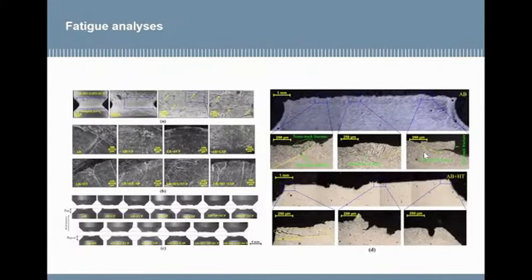Apart from the improvement in the fatigue life of the samples that I'm showing in the next slide, what was interesting is that we expected the fatigue fracture to happen from the notch root that is supposed to be the most critical section. But because of these irregularities that we have on the down skin of the notch area, in most cases in the as-built and also heat-treated samples, the fracture was always happening on the down skin. And the post-treatments were able to displace the fracture surface and get it back to the most critical area. So they were eliminating the effect of the irregularities on the down face, and then bringing it back to the critical area that should be the notch root.